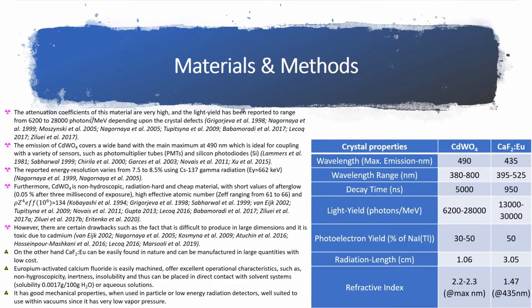Its energy resolution varies from 7.5 to 8.5% using cesium-137 gamma radiation. Cadmium tungstate is non-hygroscopic, radiation-hard, and also cheap with short afterglow. However, there are certain drawbacks, such as the fact that it is difficult to produce in large dimensions and it is toxic due to cadmium.